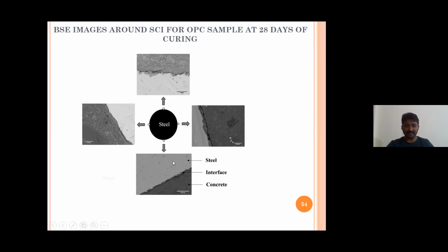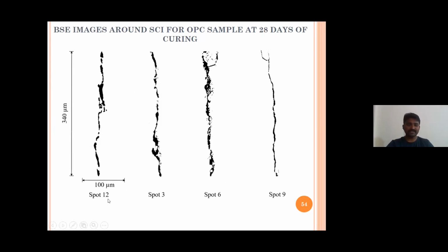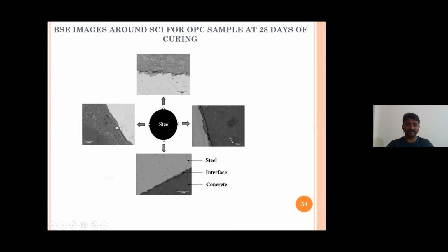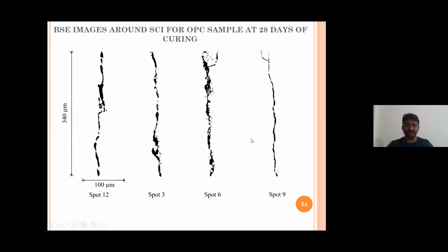Okay, so this is my steel, this is the interface, and this is my concrete. As you can see at spot 12, I've made the thresholding and I've observed the porous zone thickness this way. At spot 3, the porous zone thickness varies this way. At spot 6, this is the variation. At spot 9, this is the variation. Right? At different locations, you can identify the porous zone thickness.